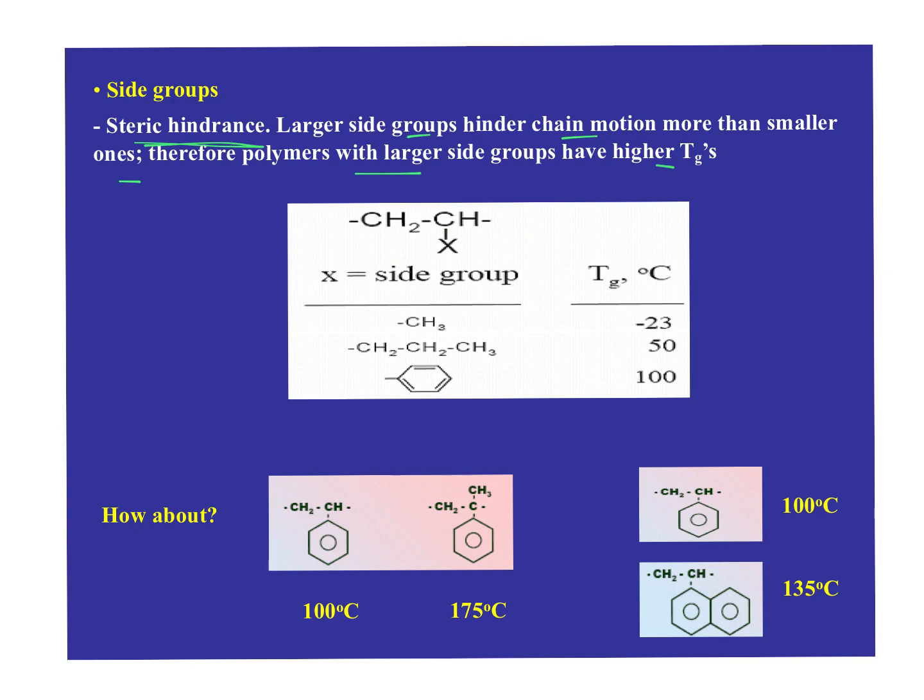And so again, we look at this set of polymer structures from the standpoint of a simple algebraic notation. If X is CH3, polypropylene is minus 23. We add a longer chain onto it, it gets more difficult to move around. Then Tg goes up to 50, and then we produce polystyrene, and we get to 100. And so how easily things can move influences the glass transition.